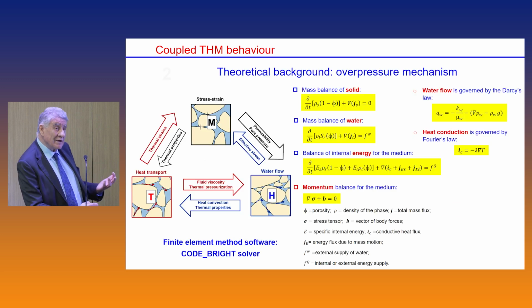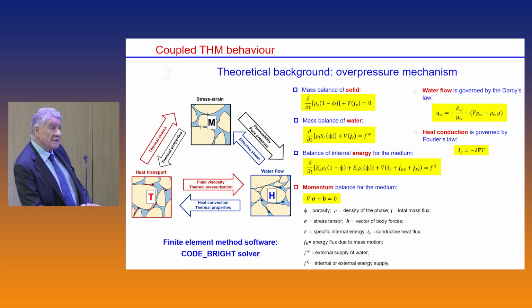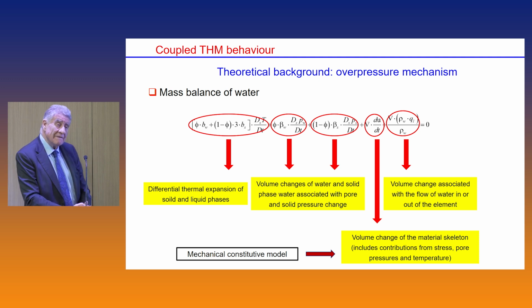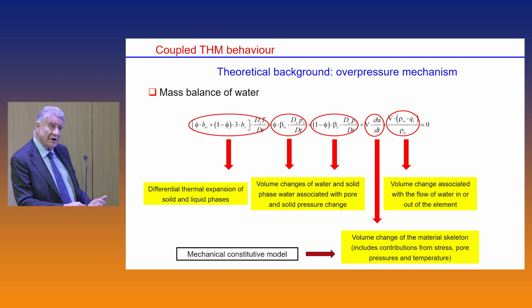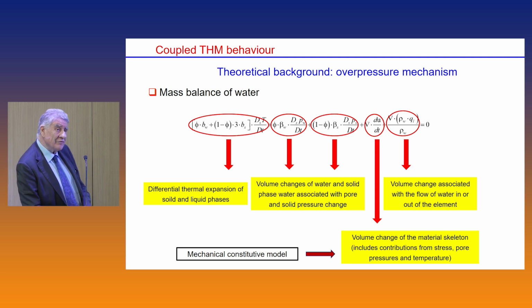The only way to approach this problem is obviously through a coupled formulation, which involves solving the mass balance of solid, water, energy, and momentum or equilibrium, introducing Fourier's law for heat conduction, which is the only relevant heat transport phenomenon, and so on. If we take the mass balance of water and we introduce there the various dependencies, you end up with something like that, which allows us to see what are the various phenomena which actually result in this overpressure. The first one is the main culprit, the main driving force, which is the differential thermal expansion of the liquid and solid phases.